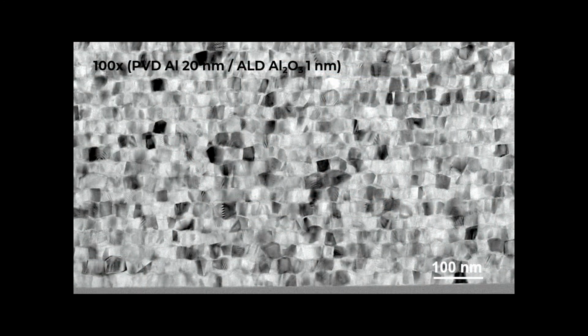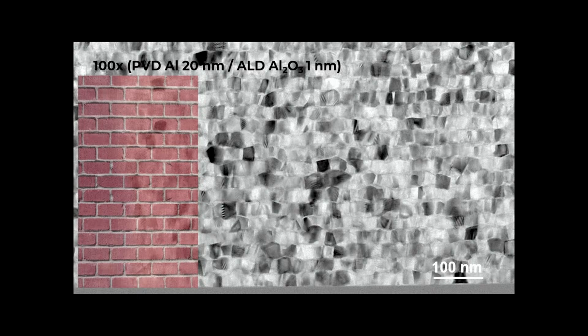You can see this a little bit more clearly. You can see that effectively by introducing these ALD films every 20 nanometers, we effectively break the grain growth of the metal film. So we can really have a very systematic periodicity of 20 nanometer grain size of aluminum, right? So this really resembles a brick and mortar structure. This is a cross-section TEM image.